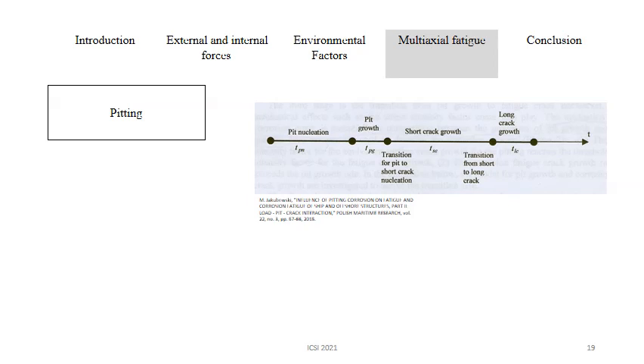Now, I'm going to explain reasons what may affect fatigue damage in small scale size. The presence of pitting in material because of corrosion can be a cause for the beginning of fatigue crack initiation where the plastic deformation under cyclic loadings is happening. It would be divided into two states named fatigue crack initiation and fatigue crack propagation. This process might be continuous as long as the mechanical behavior of the area around the pit is plastic. It can be described by the multi-axial fatigue procedure. It is interesting to say that fatigue crack initiation for those components which have no defects comes from material properties and or, accurately, mechanical properties in micro scale size.